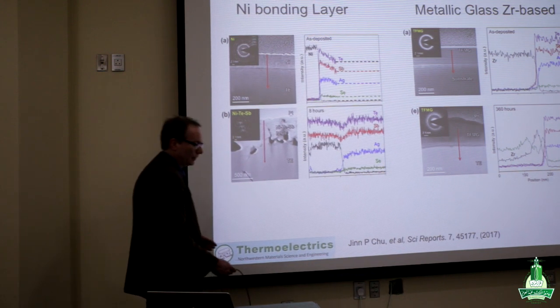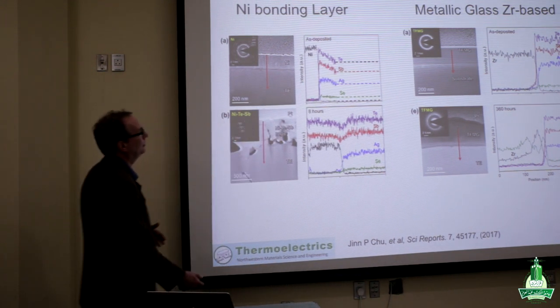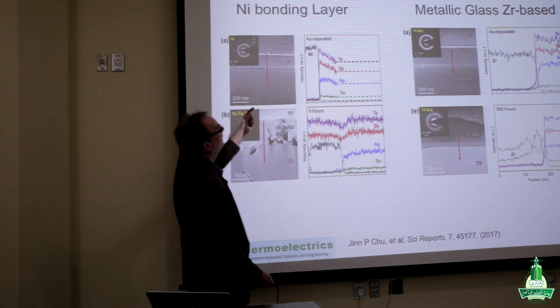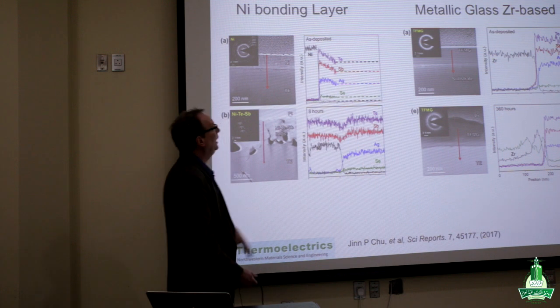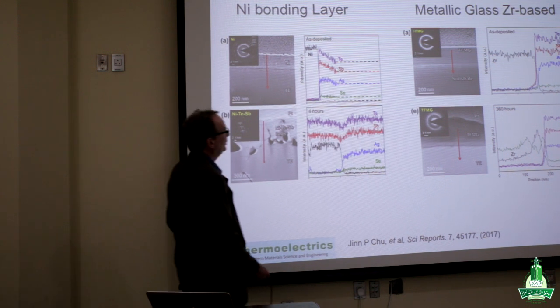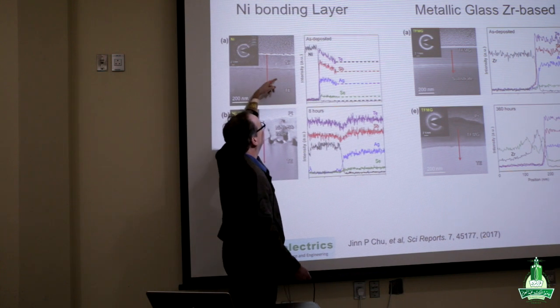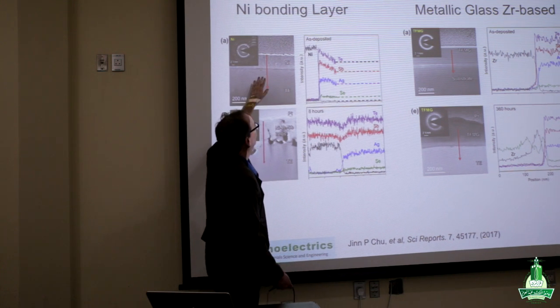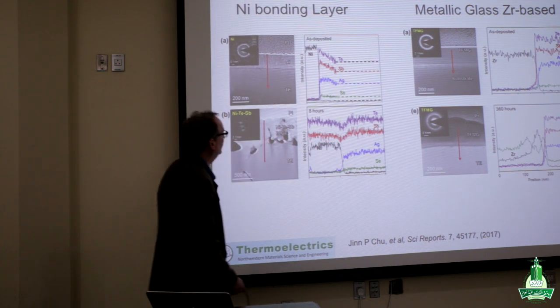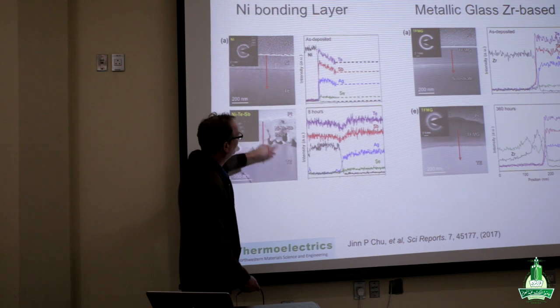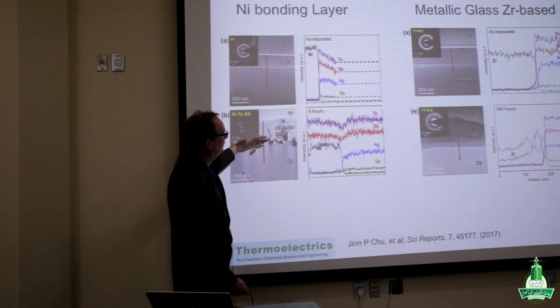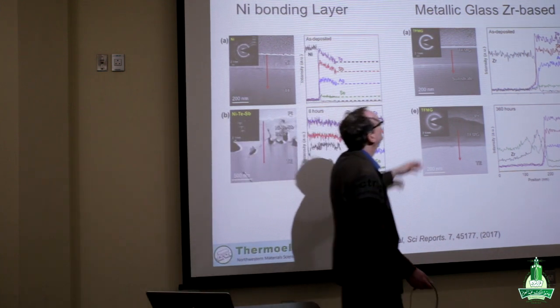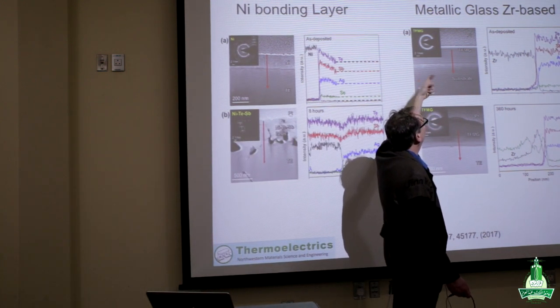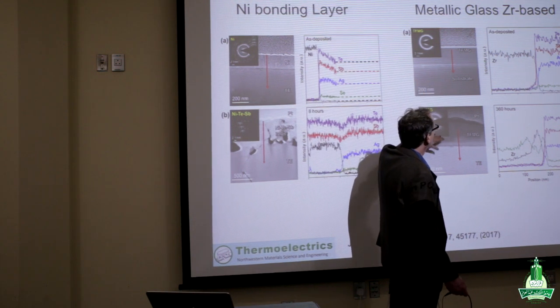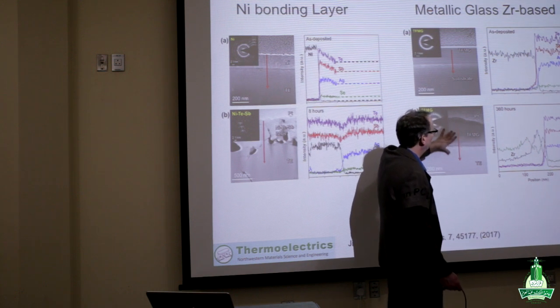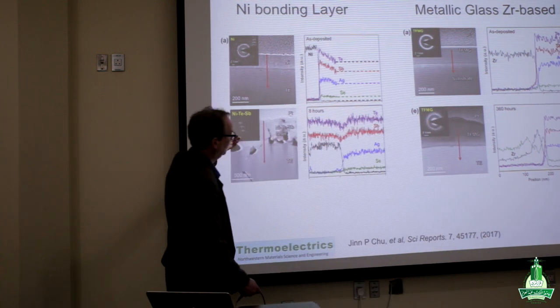And so there is opportunity for materials research in other ways. For example, looking at diffusion barriers to improve that contact, make sure it doesn't break, and also doesn't allow interdiffusion. If we tried to improve that connection with a nickel interconnect, after a number of hours we'd start to see voids being produced in secondary phases, whereas if we develop other diffusion barriers such as this zirconium-based metallic glass, we can have, after 360 hours, fairly good looking interfaces.